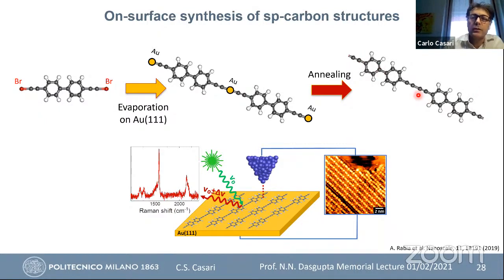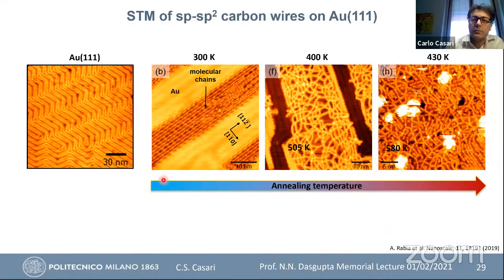Okay, so we did this and investigated it by scanning tunneling microscopy and by Raman spectroscopy. These are images of this process. This is the bare and clean gold (111) surface. When you evaporate, you see the formation of the molecular chains, and by annealing, you have a sort of modification because of the removal of the gold atoms.